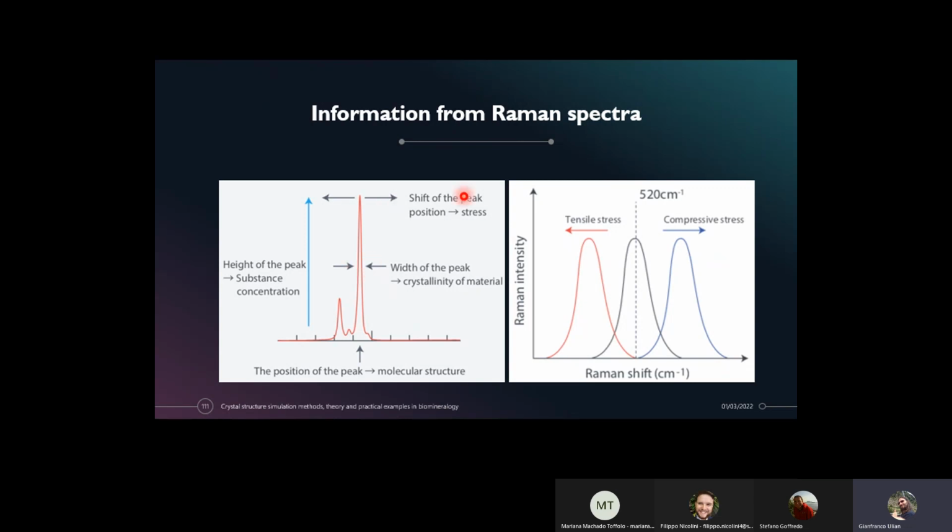your material. The position of the peaks is obviously controlled by the chemical environment of your system, but also by the stress that is stored inside your solid. For example, if your atoms are brought nearer, you are changing the environment of your atoms, so there may be an increase or decrease in interaction, and your peaks may be shifted in frequency, in wave numbers.